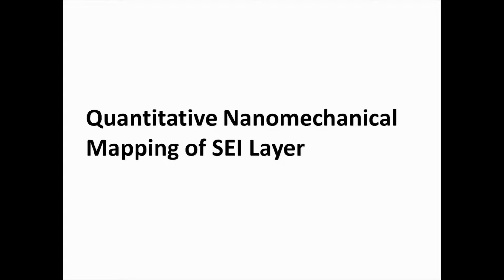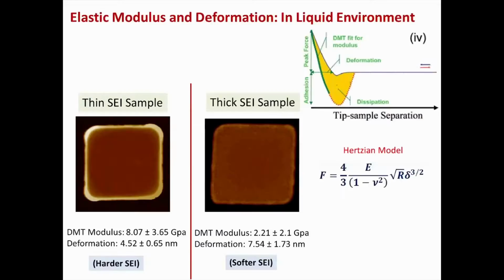One important thing which is missing right now is some kind of elastic modulus measurement, which would be useful in predicting some of the other important properties of the SEI layer. So from now, what I will be talking about is quantitative nanomechanical mapping, which is called QNM, of the SEI layer to study some of its elastic properties. As Teddy already introduced PFQNM, by applying some kind of force to the SEI layer, we can get approach and retract curves, and by fitting appropriate models to these retract curves, we can get elastic modulus values for the SEI samples.